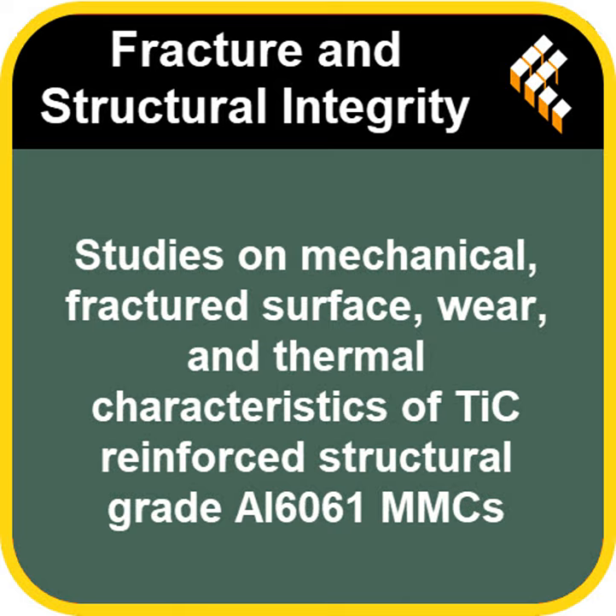But let me guess what happened to 12% TiC for CTE. Did that trend reverse again? You're absolutely right. We see that familiar turnaround. The CTE value started to increase again when the TiC content went up to 12 weight%. High this time. Still agglomeration? Agglomeration likely plays a role again, yes.